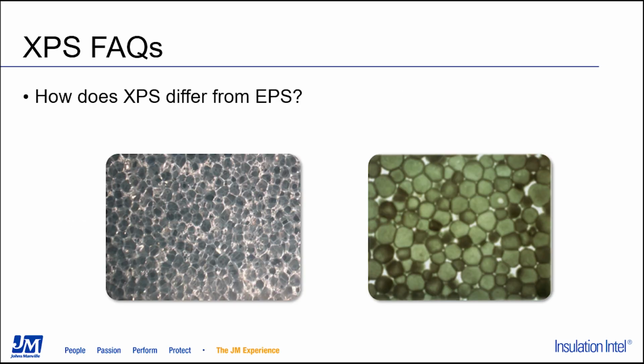Here you see some photomicrographs with XPS pipe billet on the left, and as you can see, each cell is intact and there are no voids between the cells. Compare this to the picture on the right of beadboard. You can see that each little bead in the beadboard has closed cells, but there are voids between the beads that allow water and water vapor to pass through it readily. JM has videos of water-based ink injection into both materials, and these clearly demonstrate the comparatively poor water resistance of beadboard, the ability of water to flow through it pretty readily. If these would be of interest to you, let us know.